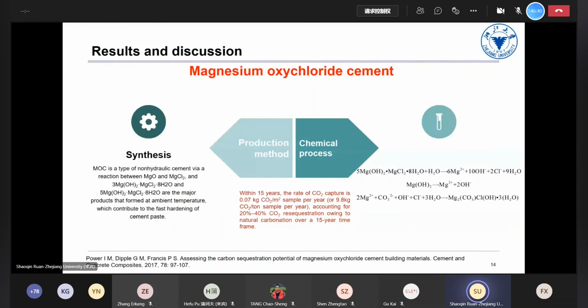Then there is the magnesium oxychloride cement, and we call this MOC. MOC is a type of non-hydraulic cement made by the reaction between MgO and magnesium chloride. Several very important phases, like phase 3 and phase 5, are the major products that form at ambient temperature, which contribute to the fast hardening of the cement paste.